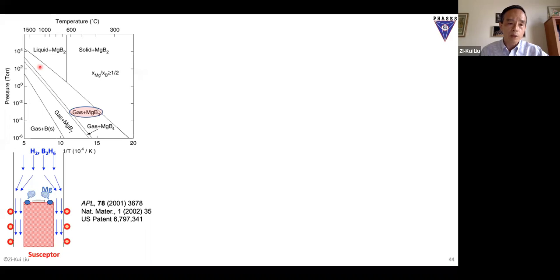So this is the window we should process in - it depends on temperature, so you should adjust your pressure. That pressure, of course, is the magnesium vapor pressure, and it's very, very high - almost impossible to control by MBE or PLD, pulsed laser deposition.